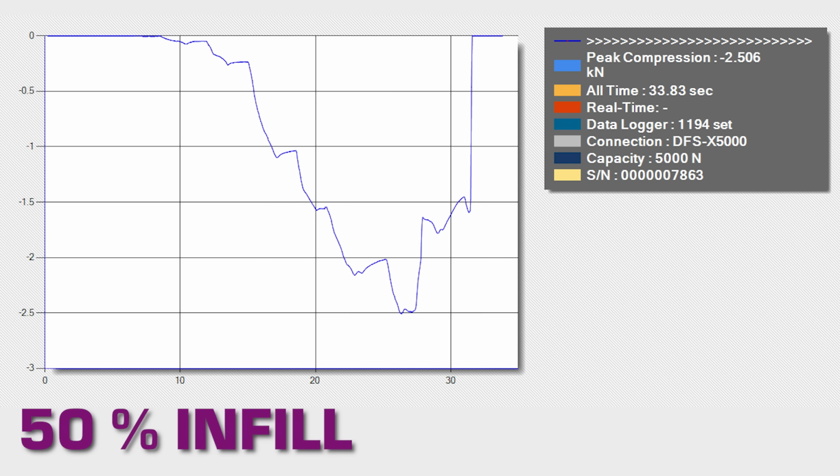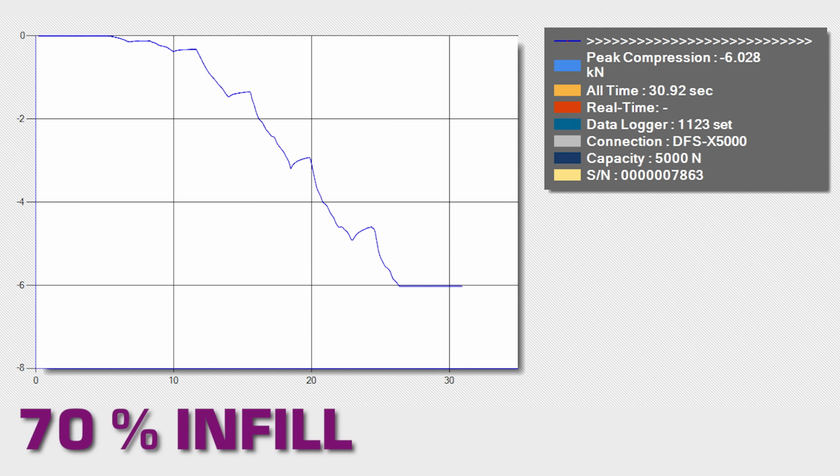And remember that if you make it fully solid, it's just about the same dynamics as a standard solid plastic part. But if you're down lower, really the most you ever really need is about 50%, and you're about as strong as you need to be. And once you pass 70, there's really not that much difference, and you'll break most of the things that it comes in contact with.